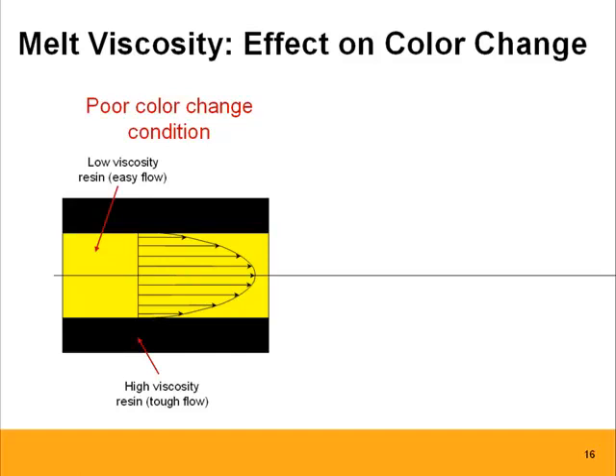It's actually one of the reasons why in plastics we're able to inject water and air into the melt stream for gas injection, for example, which have very low viscosity, of course, relative to the resin. Because of the laminar flow principle, we can push that material through the center core. From a color change point of view, of course, that is not a good situation.